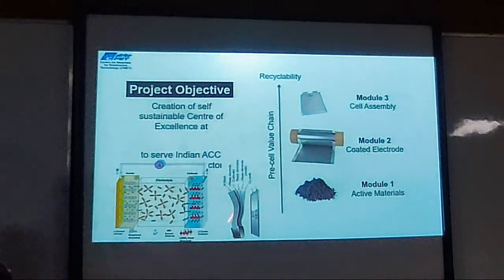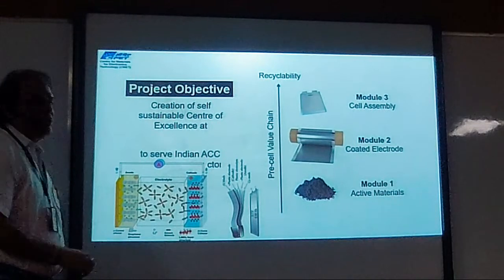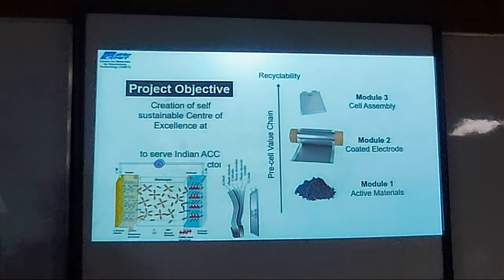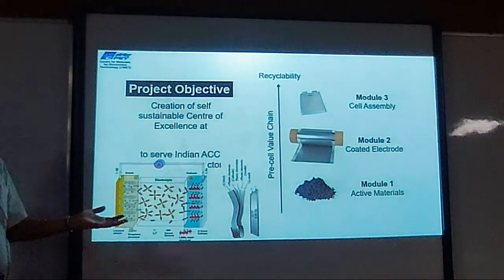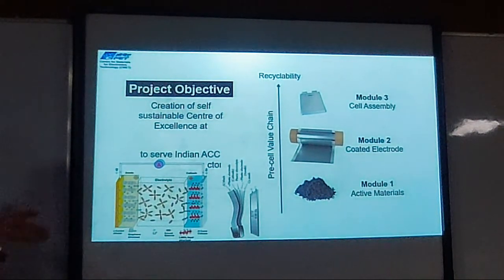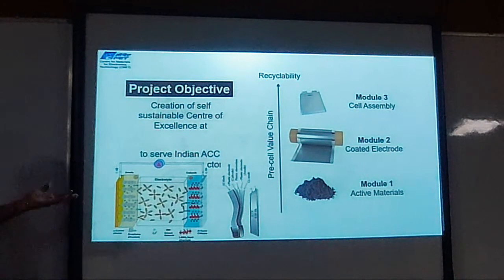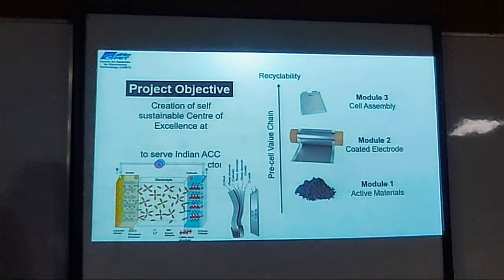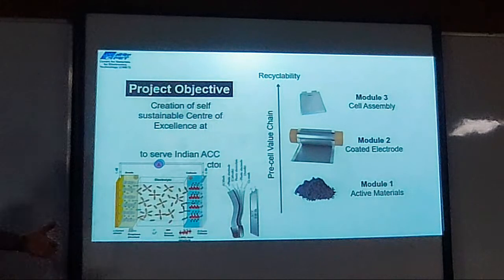What happens when we charge the battery, the temperature goes up. If the temperature goes up to 60, 70 degrees centigrade, definitely this electrolyte vaporizes, and there is swelling in these batteries. Then there will be some explosion. So we cannot charge the batteries that fast. As soon as we charge the batteries very fast, the temperature in the battery also rises very fast.